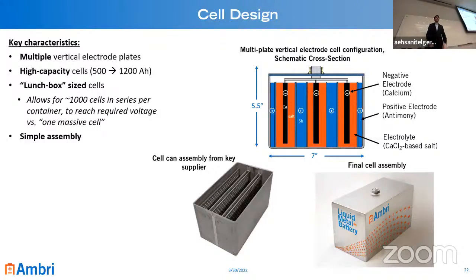Can you talk about round trip efficiency? Yes. Actually, the next slide mentions it, but because of our operating temperature and fast kinetics, we're getting 80 to 90% round trip energy efficiency, which is not quite as good as lithium ion, but better than lead acid, better than pumped hydro, some of the other competitors in the space, but we think very much good enough for this application.